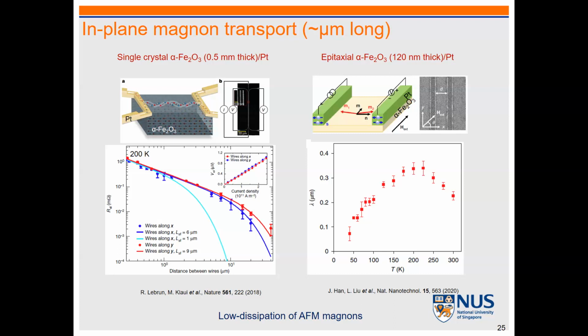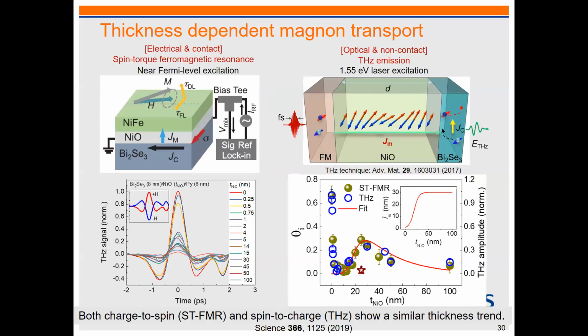Because a real device is all vertical. You look at MTJ, GMR. All of these are vertical devices, because then you have the advantage of the area, and also a very short interaction length. So in our case, we use bismuth selenide, then we deposit nickel oxide. This is an anti-ferromagnetic insulator. Then we put nickel-iron on top. Then we measure conventional ST-FMR. So this is the signal as a function of nickel oxide thickness.